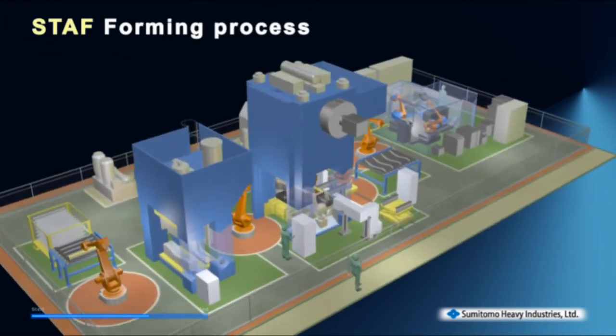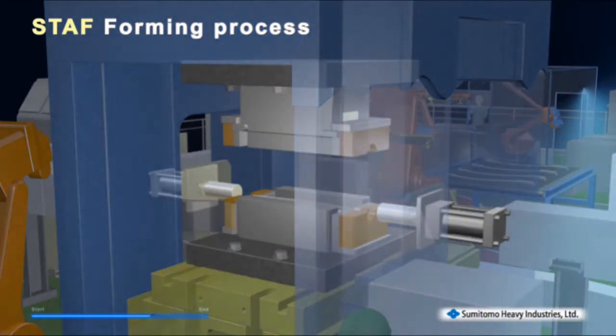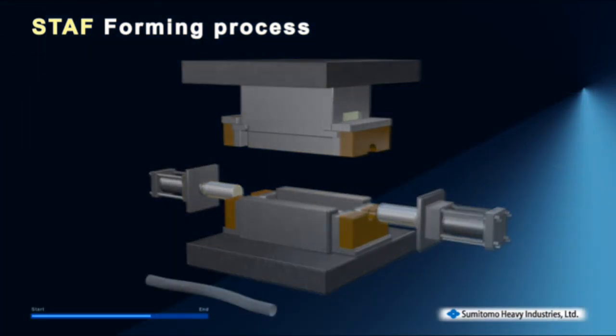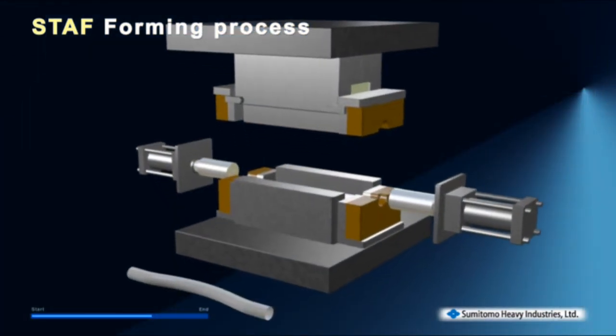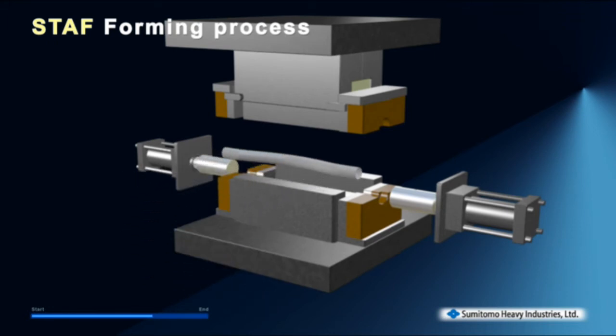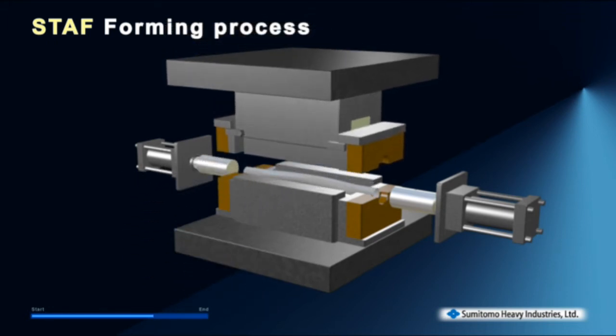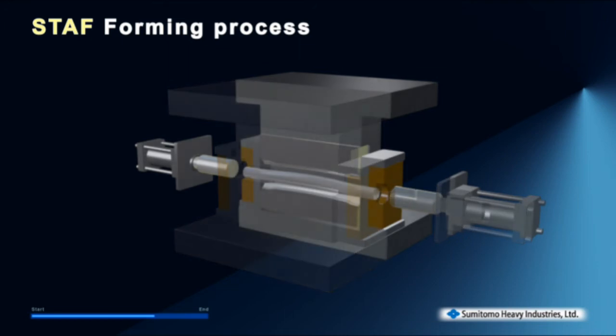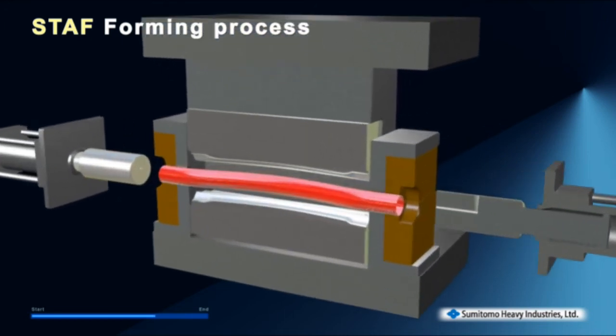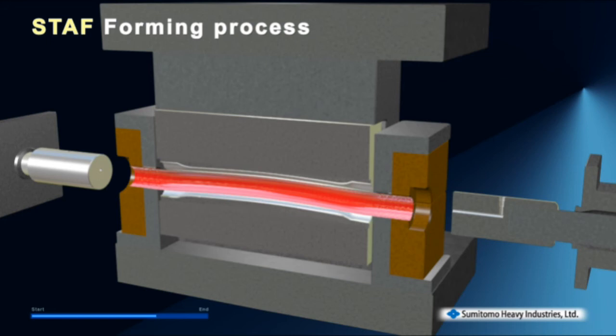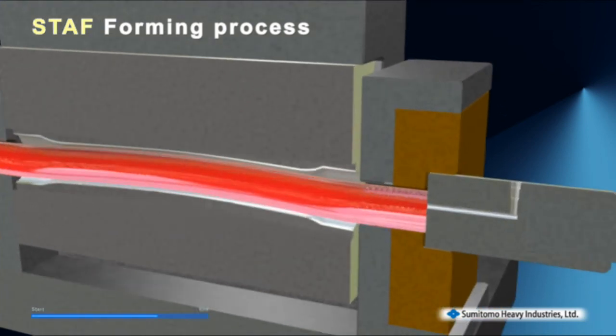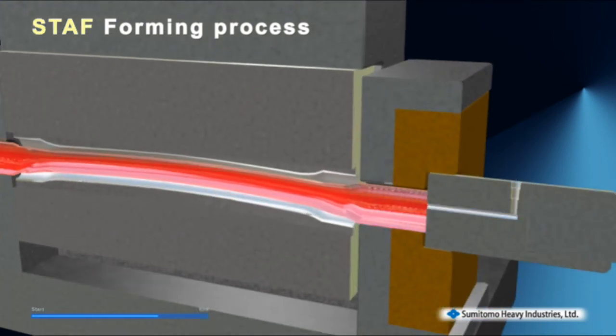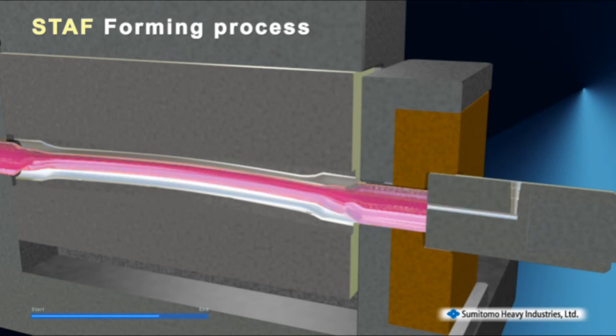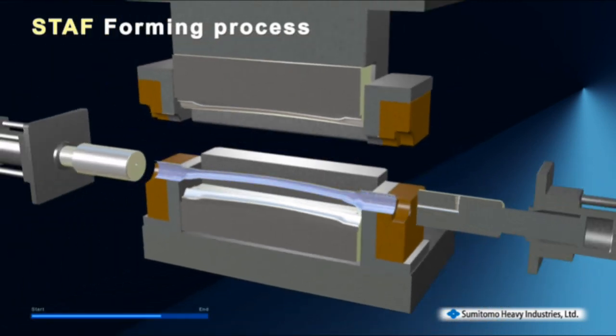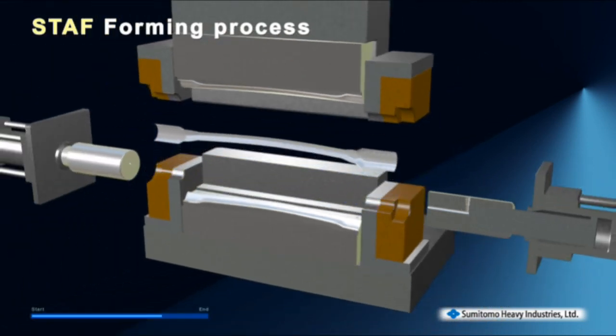So how do we use the die to create a flanged, continuous, irregular shape with a closed cross-section in just one step? We set the pipe in the press die, enable the electrodes and joule heat. After heating, we close the die. We supply high-pressure air and shape the flanges. We again inject high-pressure air to press the pipe along the inner surface of the die, thus producing a flanged, continuous, irregular shape with a closed cross-section.